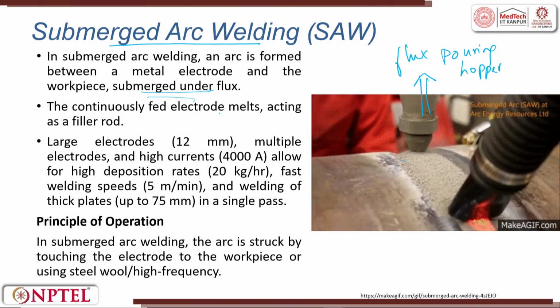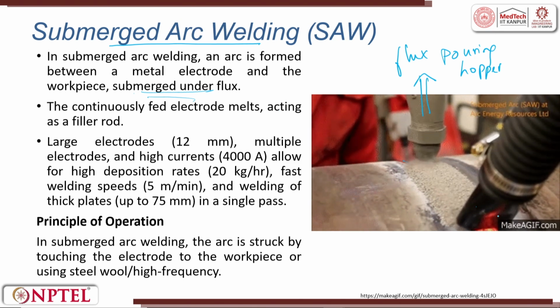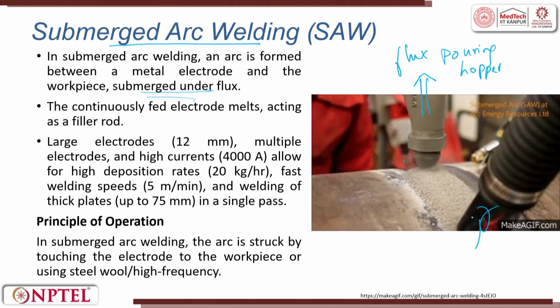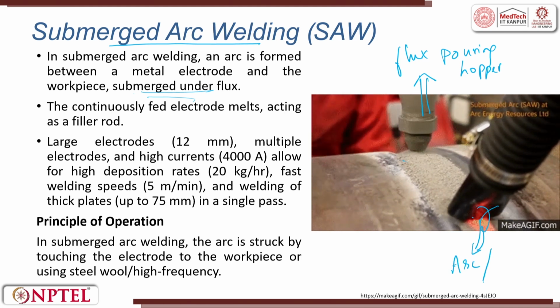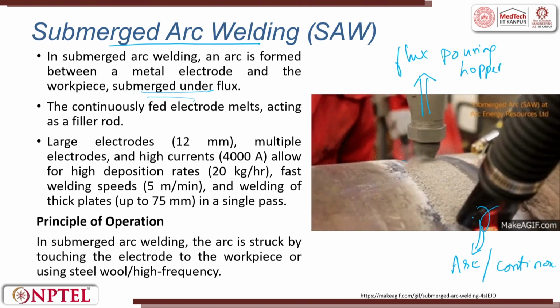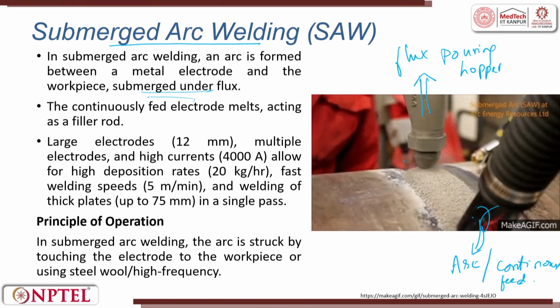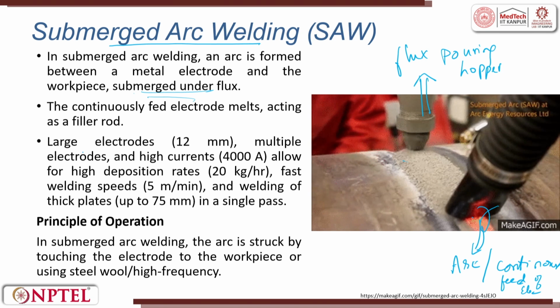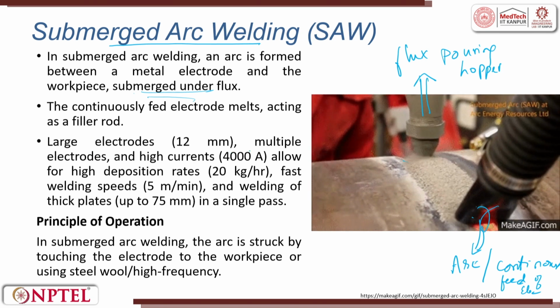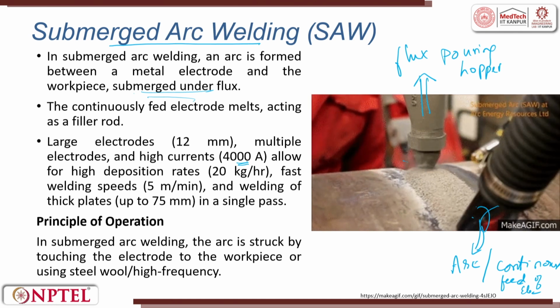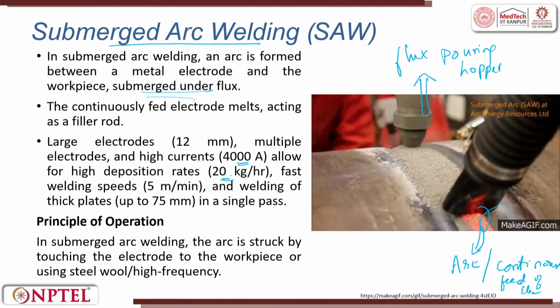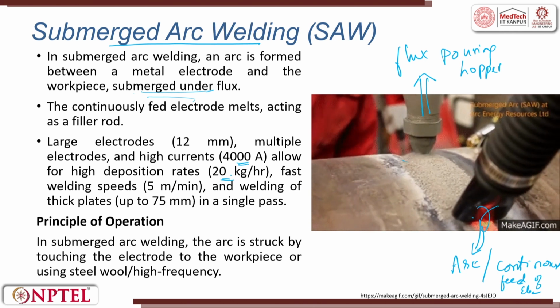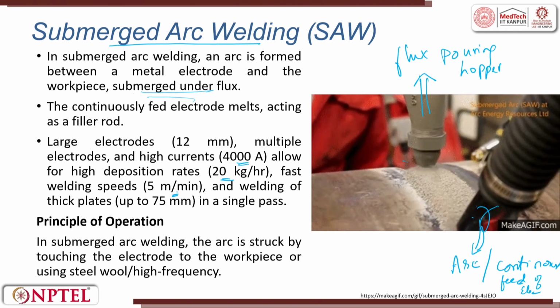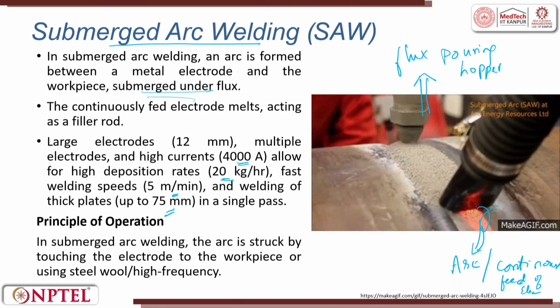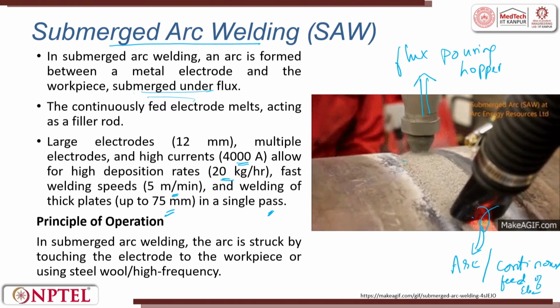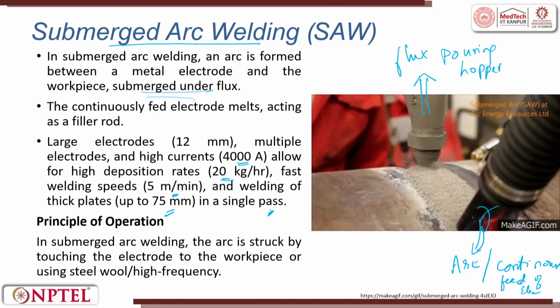So the continuous feed electrode melt acts as a filler rod. You can see here, whatever gets created is the arc, created by continuous feeding of electrode. Large electrodes up to 12 millimeter can be used, and currents like 4000 amps can be used. So the rate of deposition can go up to 20 kgs per hour. The speed can go to 5 meters per minute. The thickness which can be welded can be up to 75 millimeter in one pass. So this is submerged arc welding process.